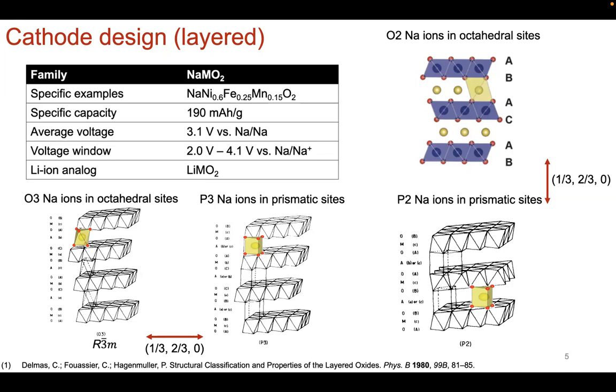Okay, and so when sodium ions go in and out, through insertion and deinsertion, they can actually start to also occupy other sites, and then you'll have rearrangement. The rearrangements will allow you to go from O3 to P3. Okay, so already you're seeing differences from sodium ion battery cathode materials and that of lithium ions, right? Because we haven't discussed these prismatic sites in layered lithium ion battery cathodes.